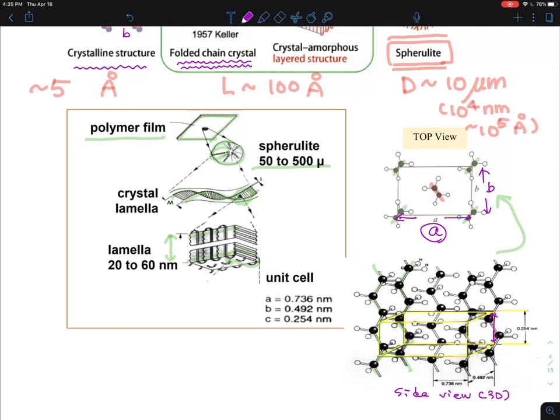So that will be the C. This is an A. This is a B, which is from the top that you see. And this is the C, which is along what is called the Z-axis. Naturally, the chain orientation, the main axis, they call it a Z-direction. That's a unit cell size of the C.